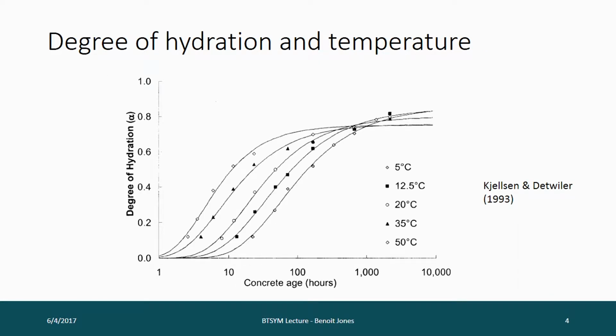So this also shows how degree of hydration increases with time at different temperatures. Going from right to left, you're increasing in temperature. And you need to notice it's a typical S-shaped curve. But also, if you were to find some sort of formulation that took account of some kind of equivalent time, you could make all those curves line up. So if you know the temperature history over time, you can integrate it to find the current degree of hydration. And people have been making use of this since the 1950s to measure the maturity of concrete.